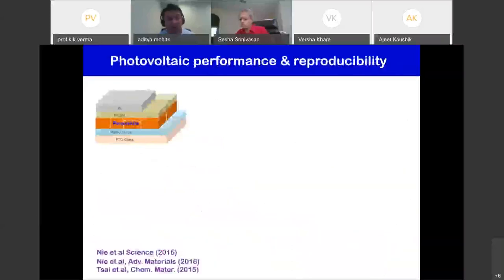What we did was we took these types of films and made these simple devices where you had your FTO glass, which is a conducting transparent oxide, PEDOT:PSS, which is a hole transport. It's a selective contact which likes to collect holes, the positive charge. You put down perovskites and you have PCBM or C60, which is a selective contact which likes electrons. And then you just put an electrode like aluminum on top.